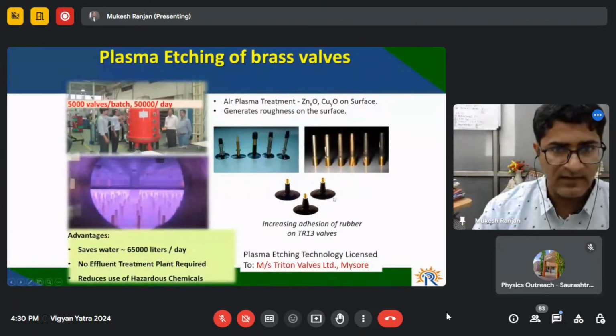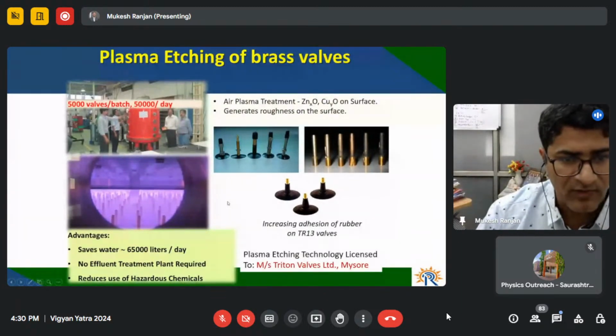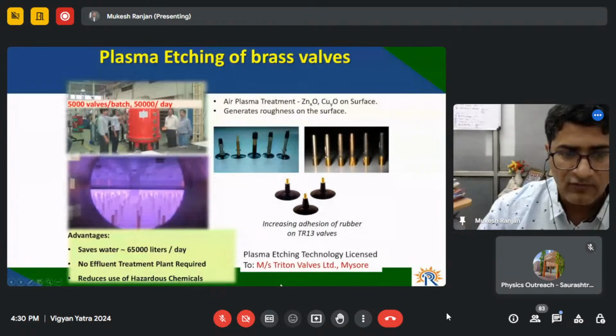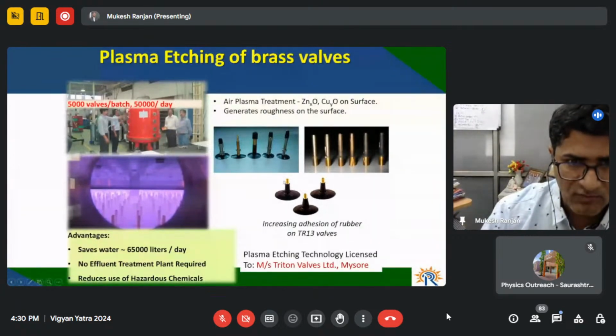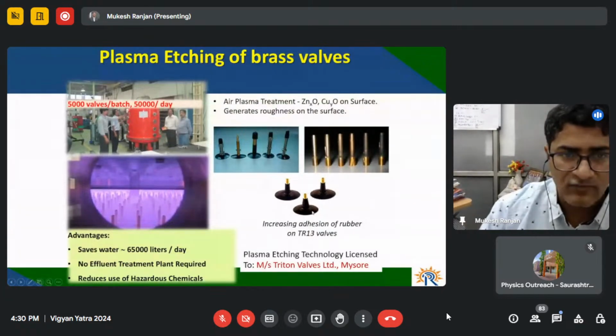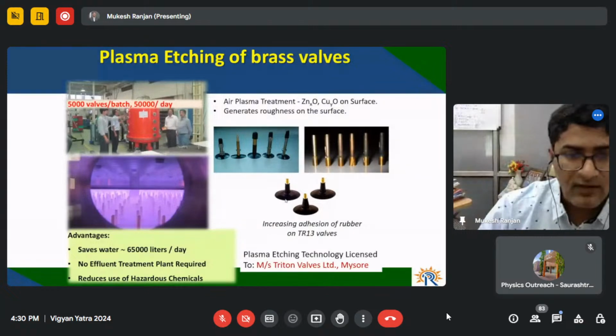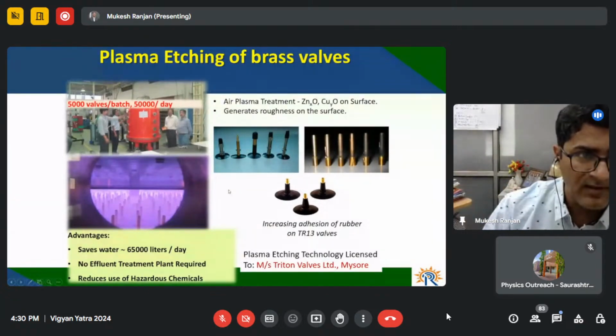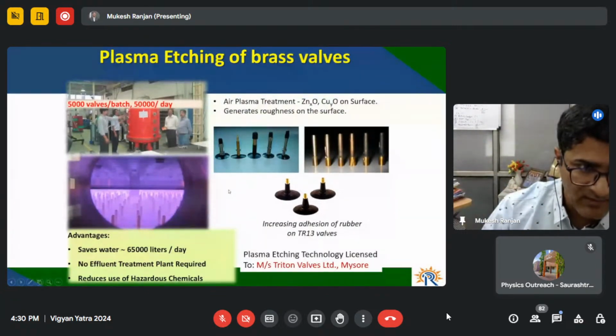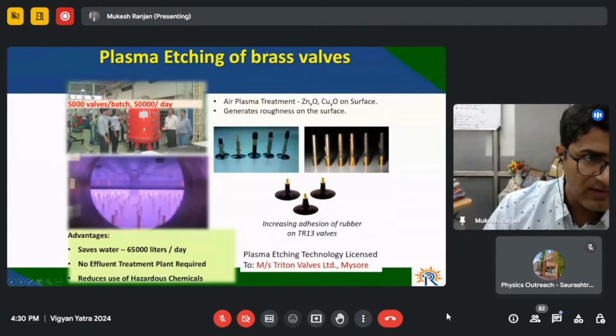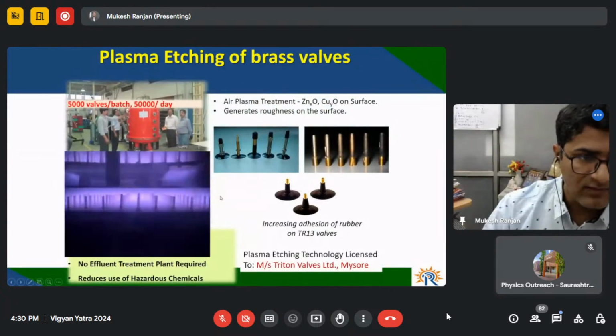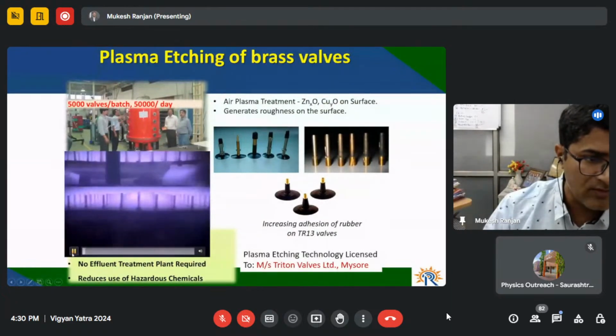There is a company which is the largest manufacturer of this kind of valves. In all tire tubes, you have a brass to rubber bonding. This is what you see on your screen. This brass to rubber bonding has to be done in a very clean manner. This company approached us to ask whether it can be done with the help of plasma. So we developed a very big chamber where thousands of such brass valves can be treated. And you can see that this treatment is going on.